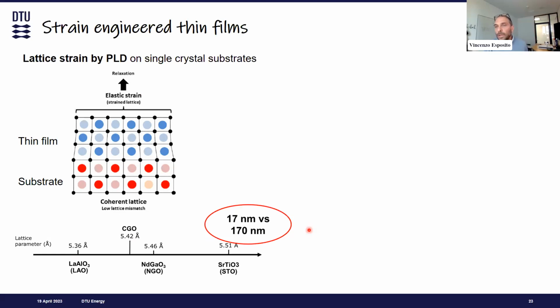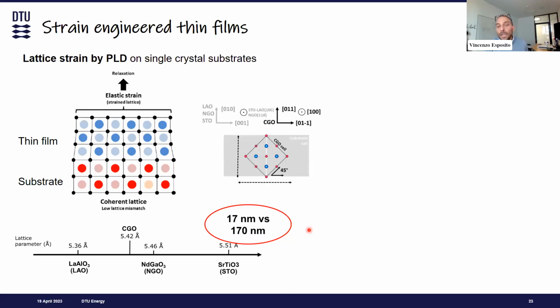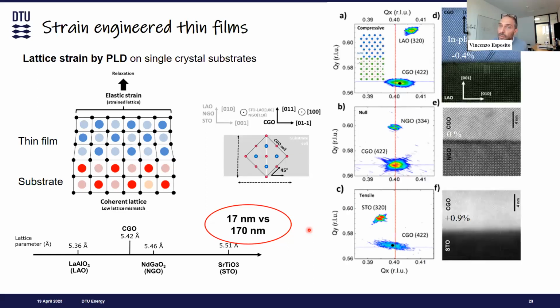It's not uniform, but it can be averaged as more or less uniform over the whole thickness. However, when we go to a thicker film, the effect of the substrate, so the interface between the film and the substrate, diminishes. And at the end, we basically get a fully relaxed system. So if we compare, for example, three films on three different substrates, thin and thick, we immediately see that the lattice in the thin film will change shape because of the influence of the substrate.